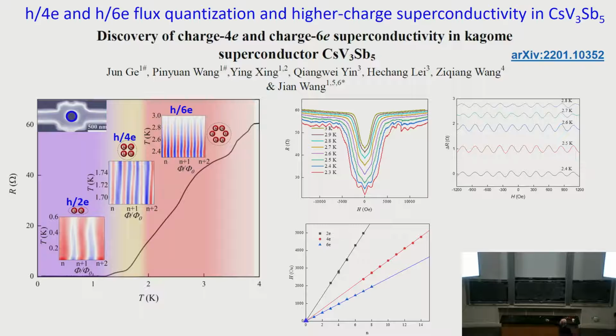All of these were obtained with the inner hole area as the effective area for calculating the flux. This is actually different from what I was just showing for the conventional superconductor. You should have used something in the wall, right? Should not be this. And this is the reason this paper is still under review. Spent a year and a half at Nature, and now it's at Physical Review X. So we're hoping that it's going to be published soon, right? So the argument is, you don't know if it's actually 2e, then you use a bigger area. Then we say, then what about the 4e? 4e is fractional. 2e is fractional. So the reviewers are actually willing to accept fractional excitations rather than higher charge superconductivity.